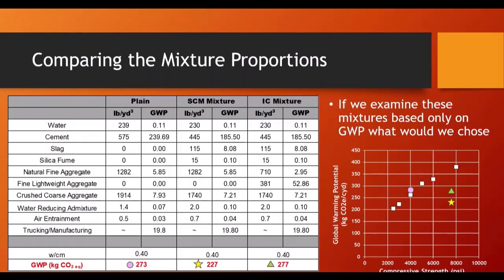Now, one of the interesting things when we start to look at the internally cured mixture, and we do our tally, we find out that we had our original mix, which was the Class C mix, which had a global warming potential of 273. We dropped the global warming potential by using slag in that mixture and replacing cement with that. But we see the global warming potential go back up when we replace sand with the manufactured lightweight aggregate sand in the system. So we're back up to that 277 value.